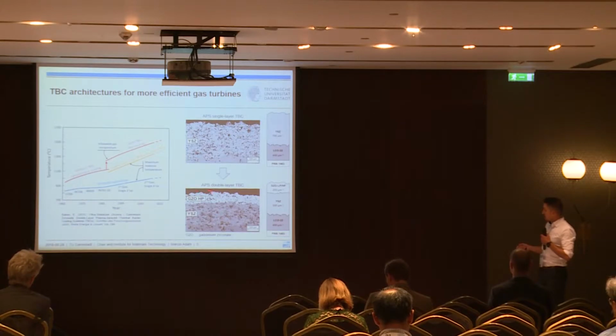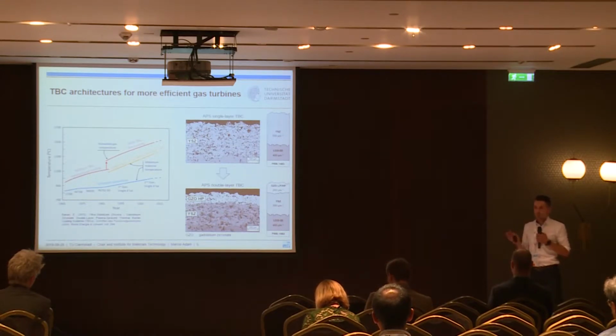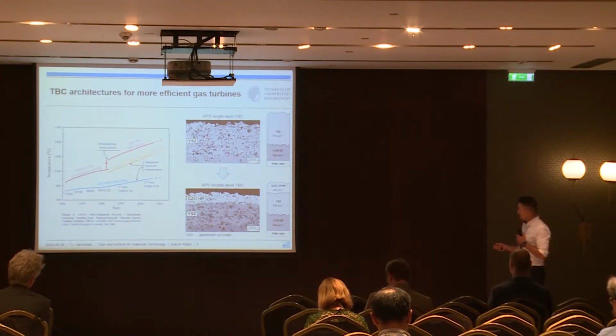To get to this point, we made an atmospheric plasma sprayed double-layer coating consisting of a conventional system, and on top of that an additional layer made from gadolinium zirconate. Gadolinium zirconate is predicted to withstand temperatures up to 1,500, maybe 1,530 degrees Celsius. So that's the double-layer thermal barrier coating we talk about on the next slides.